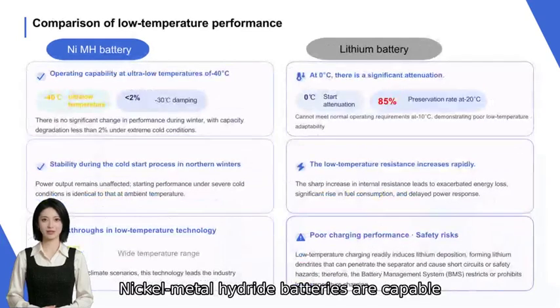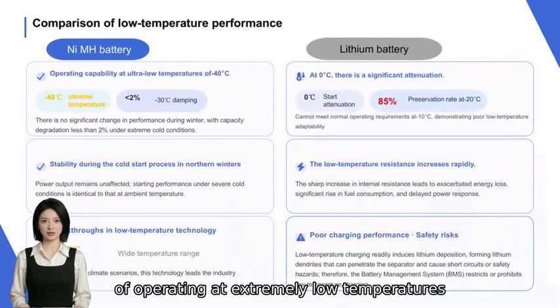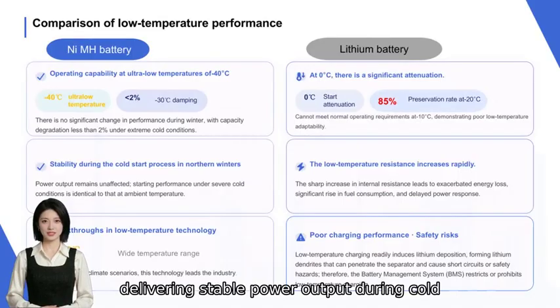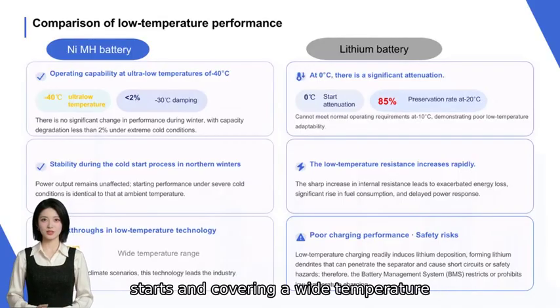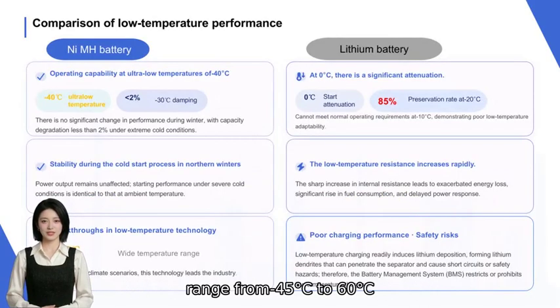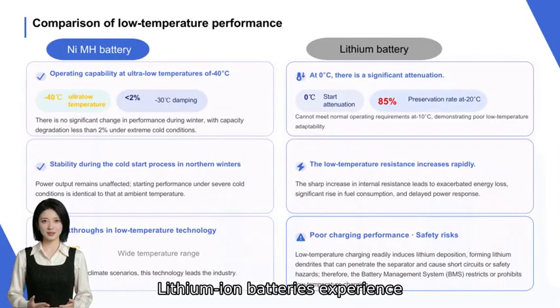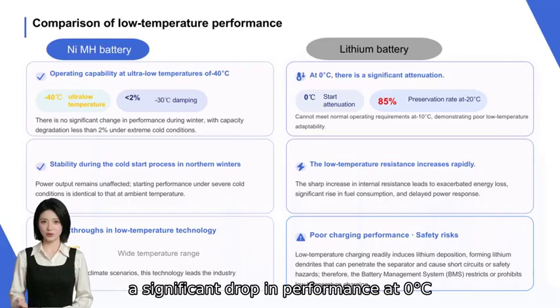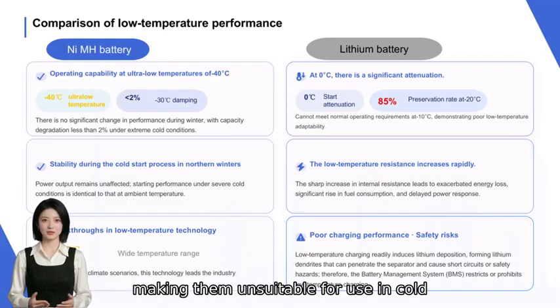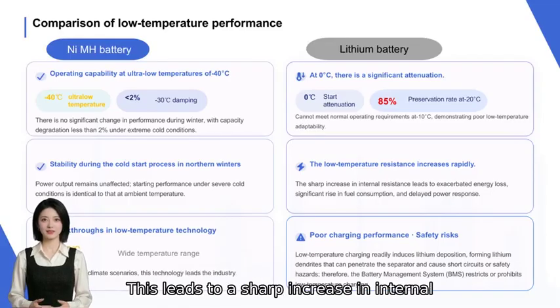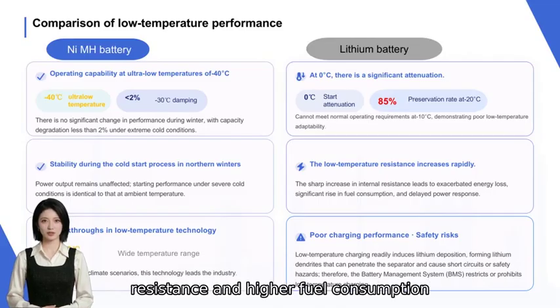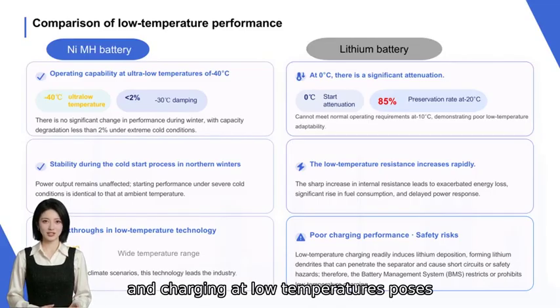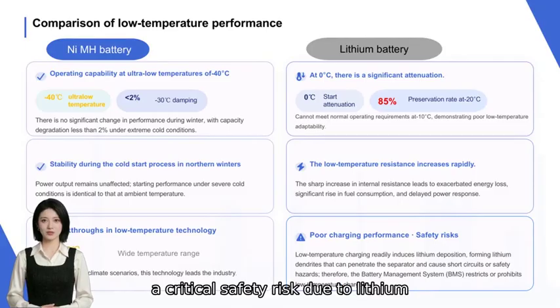Nickel metal hydride batteries are capable of operating at extremely low temperatures, as low as -40 C, delivering stable power output during cold starts and covering a wide temperature range from -45 C to 60 C. Lithium-ion batteries experience a significant drop in performance at 0C, making them unsuitable for use in cold climates. This leads to a sharp increase in internal resistance and higher fuel consumption, and charging at low temperatures poses a critical safety risk due to lithium dendrite short circuits.